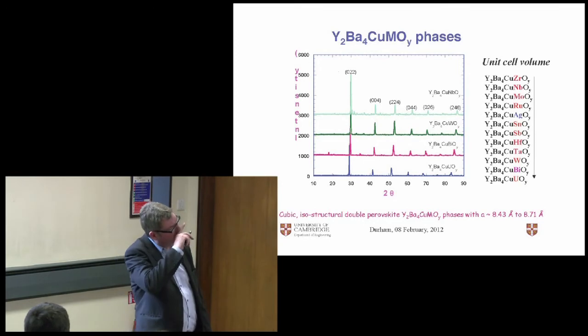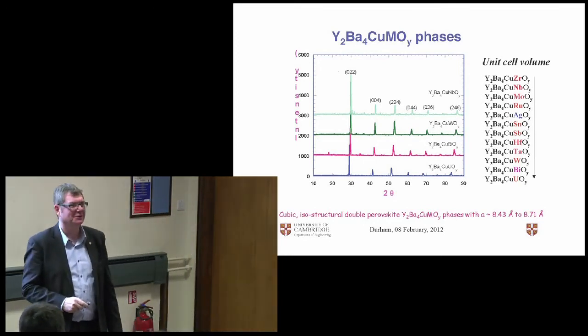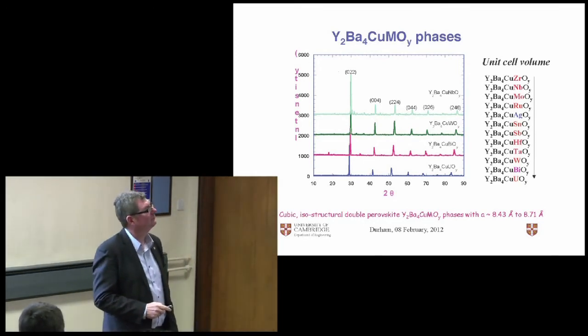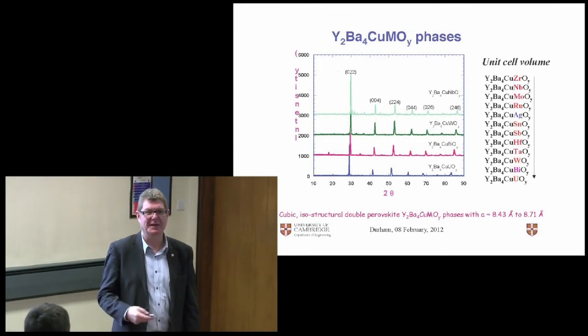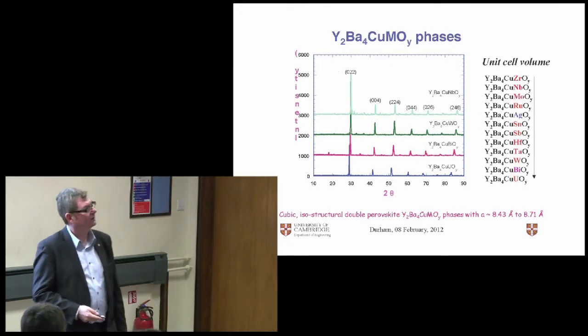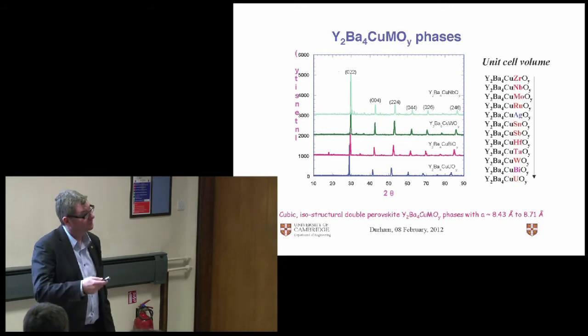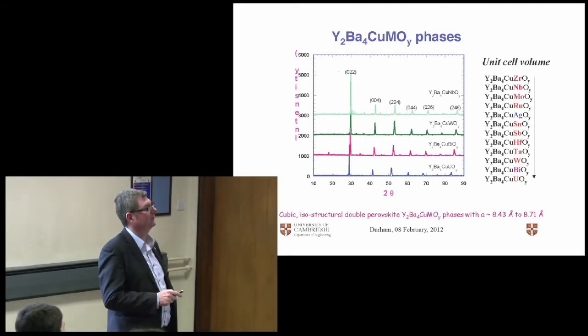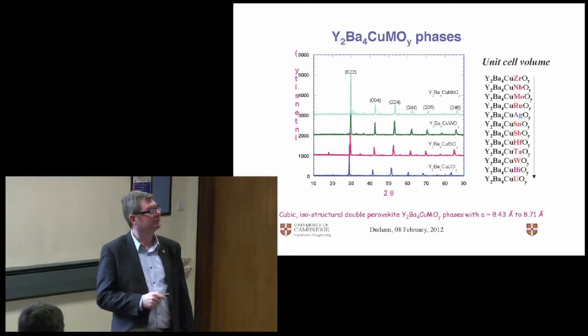And you irradiate it, then you can get fission fragments that do local damage, and they form very good pinning centres. So I thought, well, we can't really do the fission bit. So what if we get depleted uranium and look for a chemical effect? But at the time I was doing some work with British Nuclear Fuels and Urenco, I thought this might be a way of getting some money out of them.